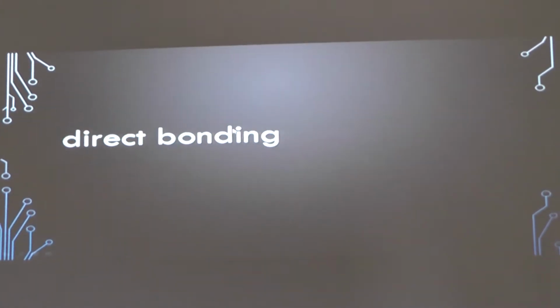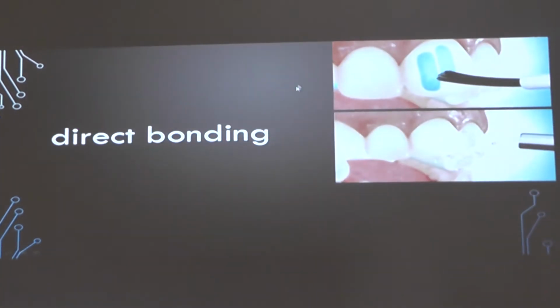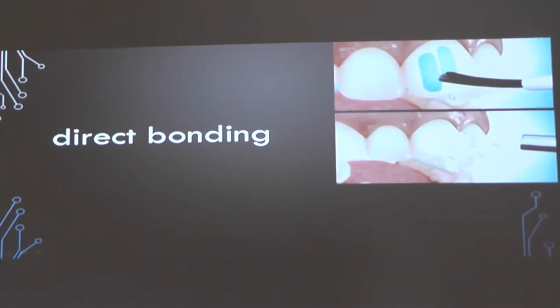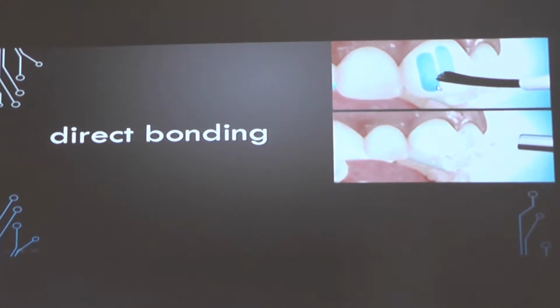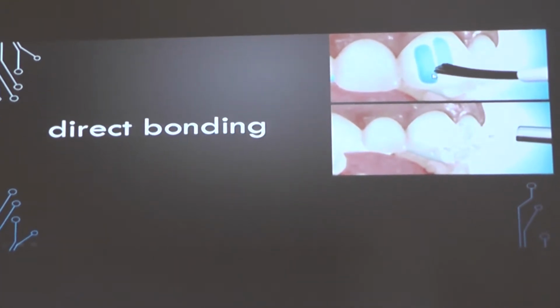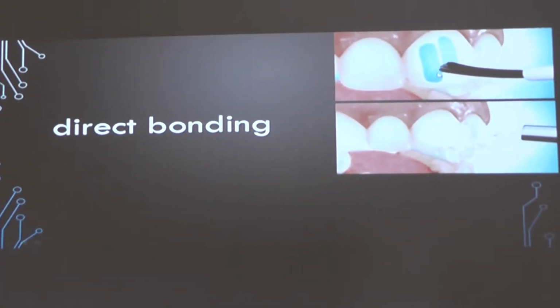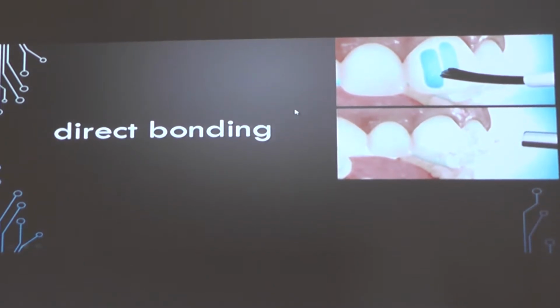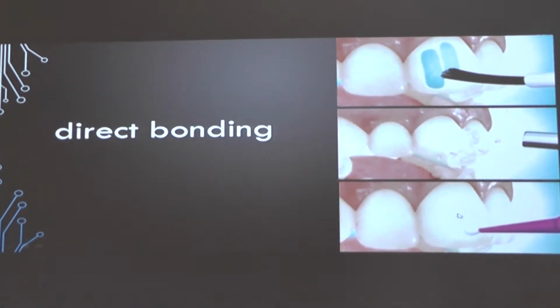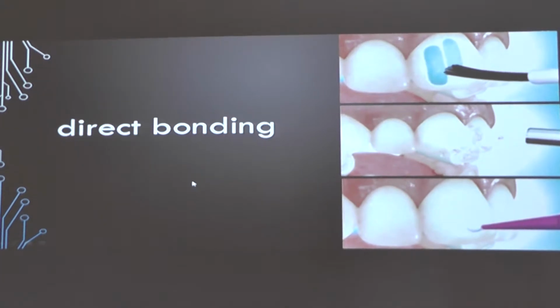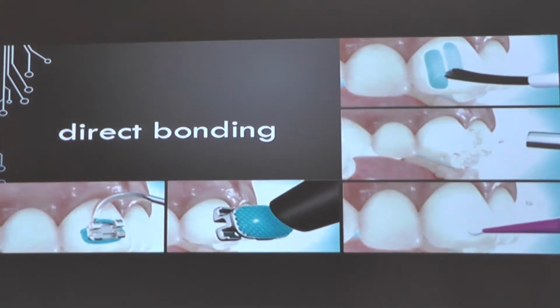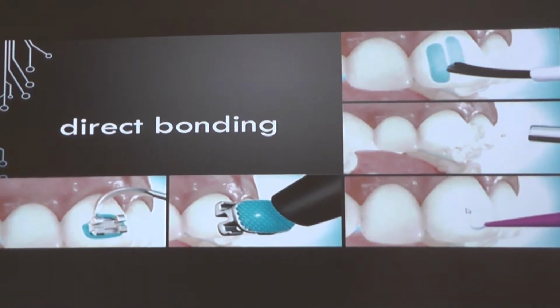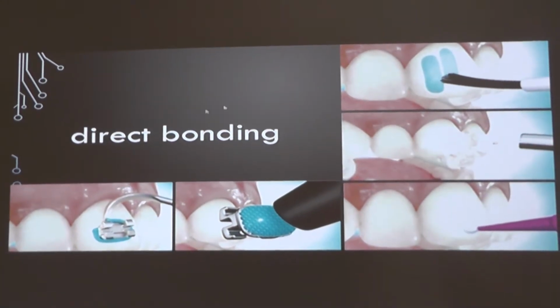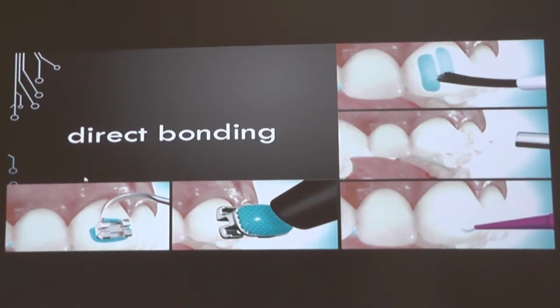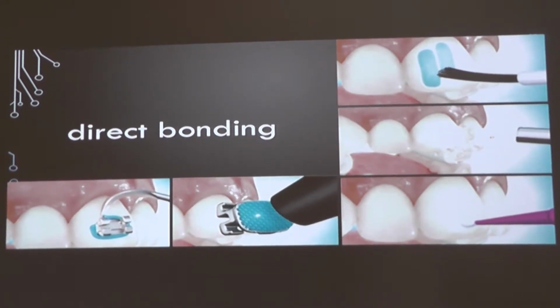And the direct bonding technique you all know. So we etch the surface of the enamel so that after 30 seconds the surface already frosts, and then the acid is rinsed and primer is applied most often, but we will also talk about this. And this primer can or may not be polymerized at this point. And then the adhesive is placed, the bracket is positioned, and all the excess is removed.